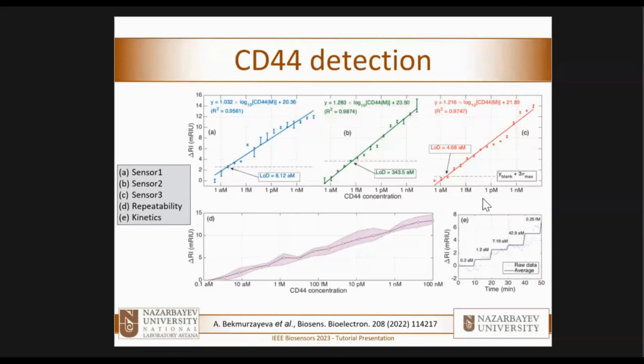The negative part is that, of course, it's operating on a wide range. And that's quite common for optical fiber biosensors. So it's not the only one, but almost all the works, except plasmonic ones that you see, have this type of log linear pattern. It's common in some of the electronic sensors as well, but not many. So in general, not on such a wide range of detection. And for example, this is how the sensor works over time. So it's binding quite rapidly. It takes really a few minutes to have a detection, and the sensor detects. So each step of increasing concentration is detected, and the sensor has a quite low detection limit.